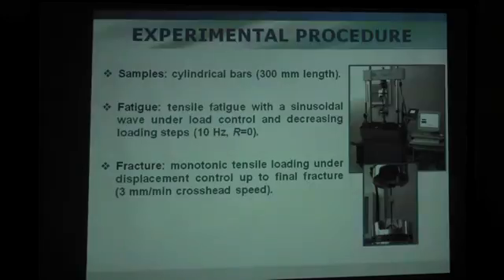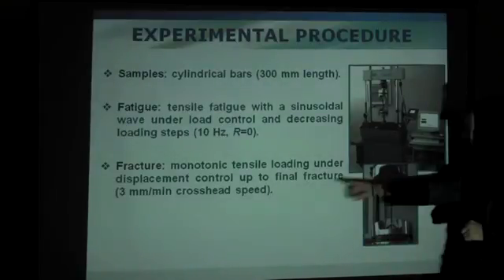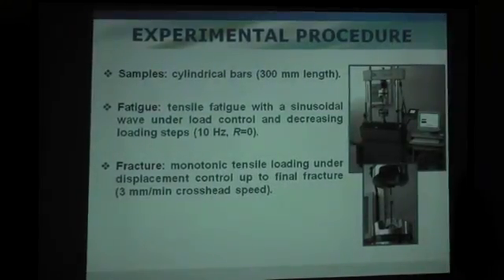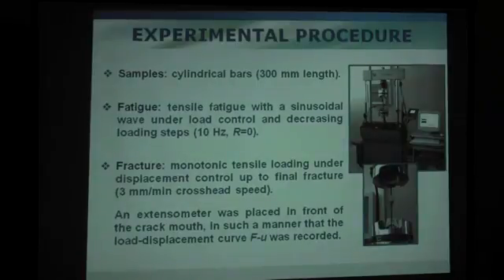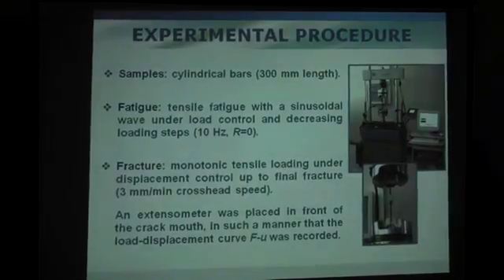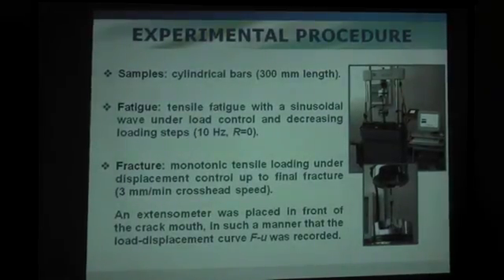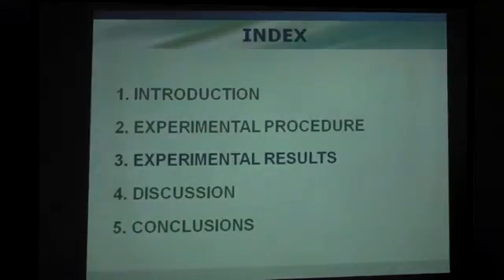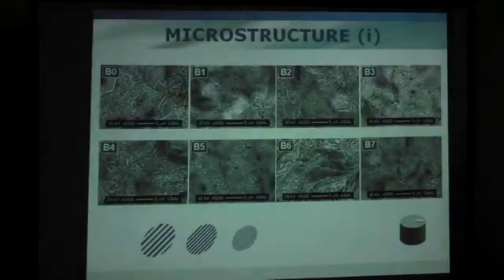Fracture, monotonic tensile loading under displacement control up to final fracture, 3 mm per minute crosshead speed. A typical fracture mechanics test. This is not a standard fracture mechanics test because they are thin wires, and an extensometer was placed in front of the crack mouth in such a manner that the load displacement curve was recorded. And now we have the records after this experimental test.